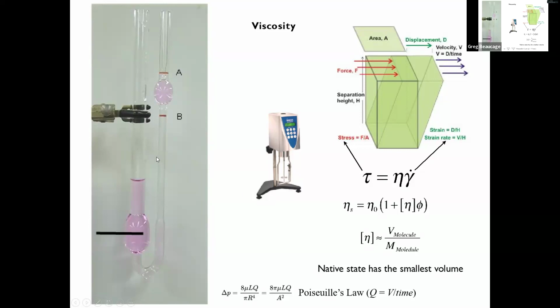So with Poiseuille's law, you have that parabolic flow field in it, so that the shear rate at the wall is highest, and the shear rate in the middle is 0 because it's a plateau. It's a bell-shaped kind of curve. So the velocity profile has zero shear rate at the middle, and you have a gradient of shear rate across it. And polymers have shear thinning behavior. So at the higher shear rate, you get a lower viscosity at the walls and a higher viscosity in the middle where there's no shear. Right, so you actually have a profile of viscosities you're looking at through this thing.